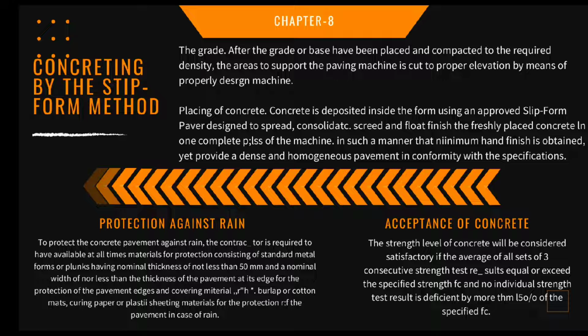Concrete is deposited inside the form using the approved slip form paver designed to spread, consolidate, screed, and float finish the freshly placed concrete in one complete pass of the machine, in such a manner that minimum hand finish is obtained, yet provide a dense and homogeneous pavement in conformity with specifications. The machine vibrates the concrete full width and depth of the strip being placed. Vibration is accomplished by a vibrating tube or arms working in the concrete or with a vibrating screed or pan operating on the surface of the concrete.